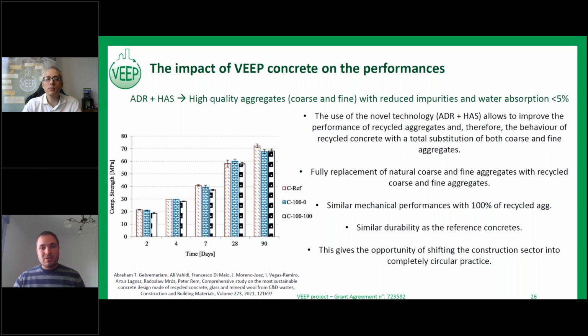In this case, as a result in new concrete, you can see the compressive strength at different stages of a reference concrete with the natural material, the second one with 100% replacement of coarse aggregate, and the third one with both coarse and fine aggregate 100% replaced by recycled aggregate.